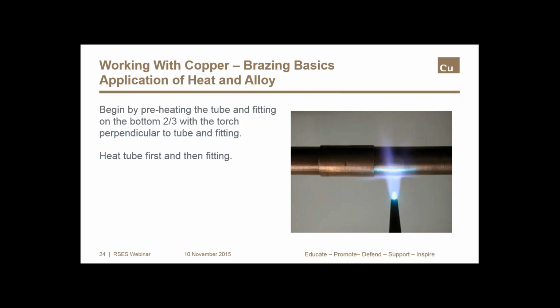So after heating the tube, switch the flame to the fitting at the base of the cup. Sweep the flame from the fitting to the tube to get uniform heating. As the fitting comes up to temperature, start sweeping the flame back and forth along the axis of the joint to maintain heat in all the parts to be joined. Remember to keep the flame moving to avoid damaging the tube or the fitting. If cast fittings are used, exercise caution to avoid excessive heating that might crack the fitting.